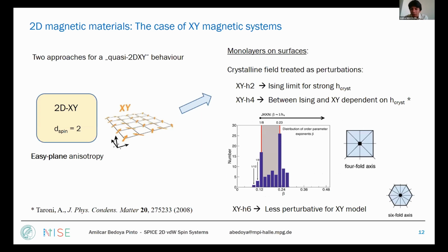So I want to get a bit more detail on the case of monolayers on surfaces, and how people in theory treated the crystalline fields as perturbations to the ideal XY model. When you assume a twofold symmetry, which is called XY-H2, for strong crystalline fields you will get to the Ising limit. That's actually very obvious, because it's the limit of strong uniaxial anisotropy, and you will destroy completely the XY regime and enter the Ising regime. In the case of fourfold symmetry, which is a cubic system, it's highly dependent on the strength of the crystalline field, and this can oscillate between Ising and XY.